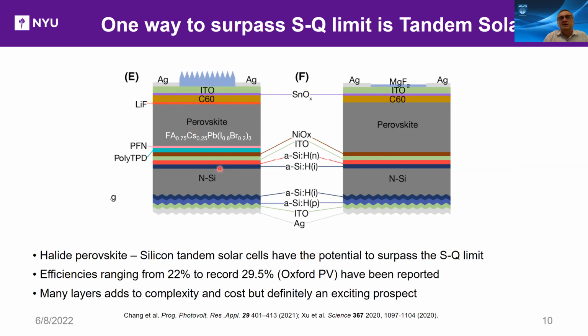This here is the latest tandem solar cell that combines silicon with a newcomer, halide perovskite, to increase the solar cell efficiencies, and efficiencies ranging from 22% to 29.5% have been reported by using silicon and perovskites. Now, I will not go through the role of each one of the layers, but one thing that you notice is that there are many, many layers. This adds to the complexity and the cost, but it's definitely an exciting prospect.